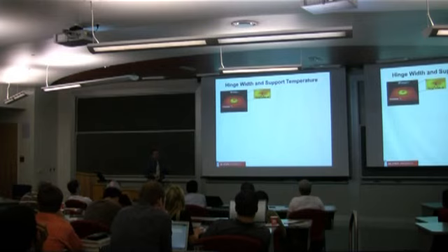So that was kind of the dirty little secret in that video. That sample is sitting on a hot plate, which basically gets it really close to the glass transition temperature. And then when you hit it with light, it goes over the glass transition temperature and folds.